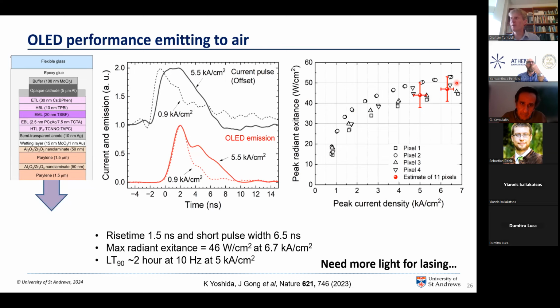It's partly because the devices have some additional non-radiative pathways when you get to very high exciton densities, and so this is one of the targets in looking at this new regime of operating OLEDs, and where we think again there's factor of 100 possibly an easy win to have in better electrical engineering of the devices. So we think that certainly the tens of milliwatts per amp sort of slope efficiencies are absolutely obtainable in these devices, and that's one of the paths that we're on at the moment to try and optimize the engineering of the full device.